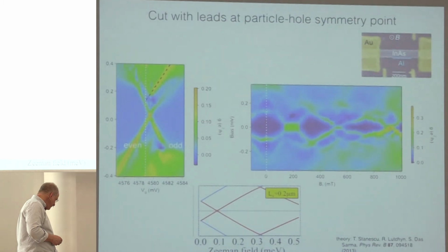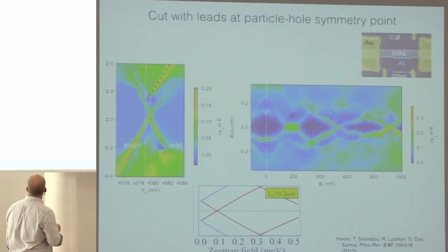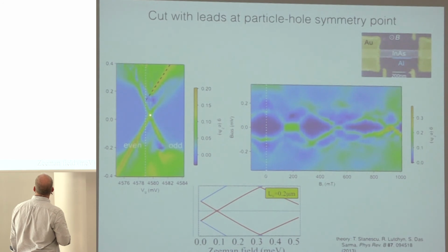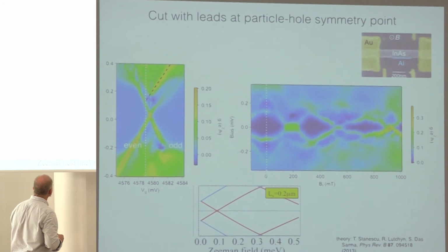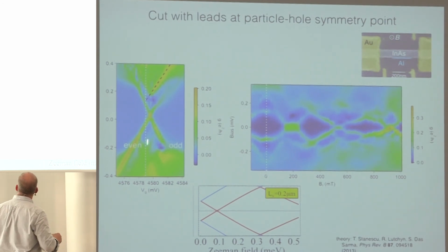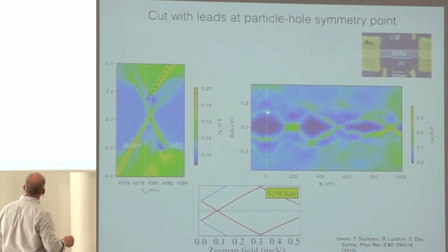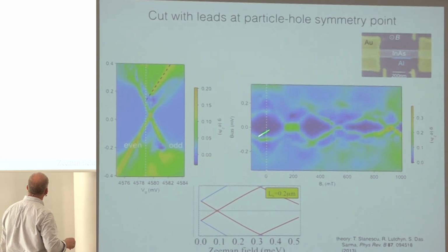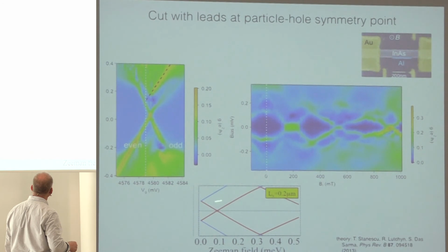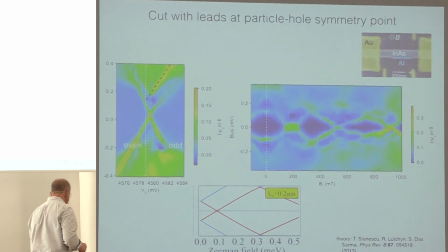Let me move on to say, you'll recall that the state was off to the left or off to the right, depending on whether it was an even or odd state. How does that depend on magnetic field? Do we eventually find that it goes back to where it would be if there were a zero energy state? Well, if we draw a line about where it would be when it was a zero energy state, we see that as a function of magnetic field, those two states come together, go apart, come together, go apart, come together, go apart. Just measured from this Coulomb blockade peak position, it doesn't look much like a Majorana, but it wouldn't because it's a pretty small device.